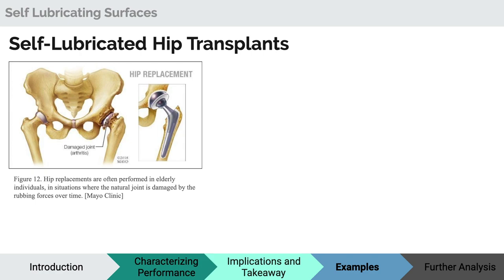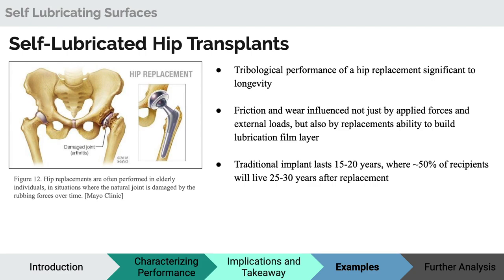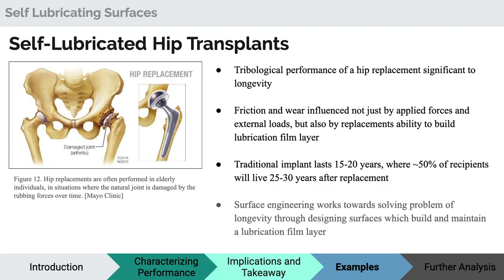Hi, I'm Danielle and I'm going to be talking to you about self-lubricated hip replacements. The tribological performance of a hip replacement has a high impact on its success and longevity. Clinical outcomes of wear testing have found that friction and wear are influenced not just by applied forces and external loads, but also by the material's ability to build a lubrication film layer. Chudhury et al. stated that around 50% of hip replacement recipients are aged between 45 and 64 and may live for another 25 to 30 years, while orthopedic implants generally only last 15 to 20 years. Surface engineering advances aim to solve this through designing hip replacement alternatives which build and maintain a lubrication film layer in the joint.